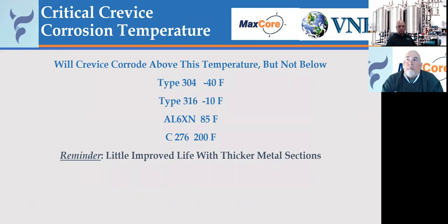Crevice corrosion will take place at some very low temperatures. In 304 stainless steel at minus 40 degrees Fahrenheit, 304 will corrode. 316L at minus 10 degrees Fahrenheit, AL6XN at room temperature, 85 degrees Fahrenheit. You get into your higher nickel alloys and you're looking at higher temperatures before you start to see crevice corrosion taking place there. And with anything like this type of corrosion, improving the life by making the material thicker will not really help, because you have to stop and think about what pitting and crevice corrosion really is: an attack to the passive layer. And once that starts to happen, it goes very, very quickly.